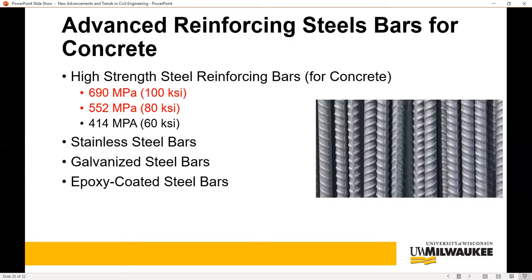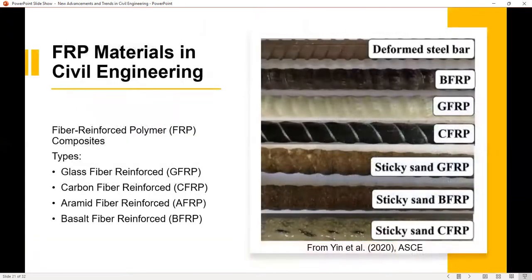They do help. However, if the quality is not good, if there are small what we call holidays, or small holes in the epoxy, the corrosion that you could get is far worse than if you hadn't put the epoxy on it. It's a very important lesson that the first applications of epoxy coated bars in the United States had major problems, and that was mitigated later.